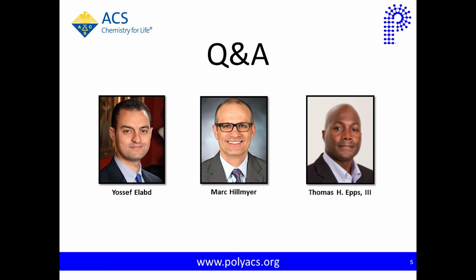Great, thanks. Christopher would like to know, Joe, there are some limitations to stability. How much is that attributed to the acrylate ester linkages in the backbone? For particularly the acrylate, it typically hydrolyzes pretty rapidly. Methacrylate, the PMMA type, minimizes that hydrolysis, but we still see a fraction of that is due to hydrolysis. But we also see the primary mechanism for the imidazolium, even on a PMMA backbone, is ring opening before we start seeing the hydrolysis.